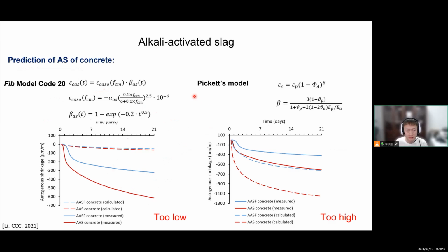And we also have the Pickett model or the Hobbs model, which are based on mechanics. So they have their physical background. There are several parameters, but it tends to overestimate the shrinkage because in their model they only consider the elastic mechanics. But here we have a lot of creep. The restraining effect of aggregates on the elastic part and the creep part are different. So the aggregates tend to restrain the creep more than the elastic part. If you don't consider the creep part, you will actually underestimate the restraining effect of aggregates. So you will then overestimate the shrinkage.